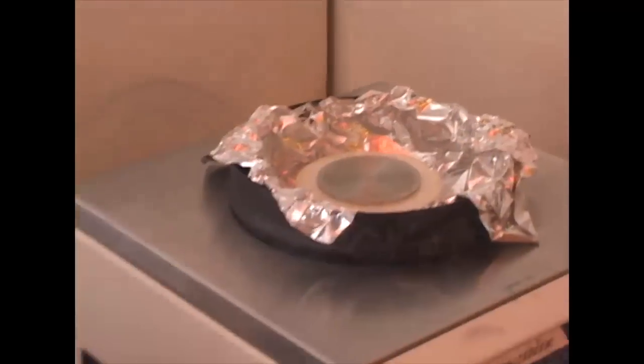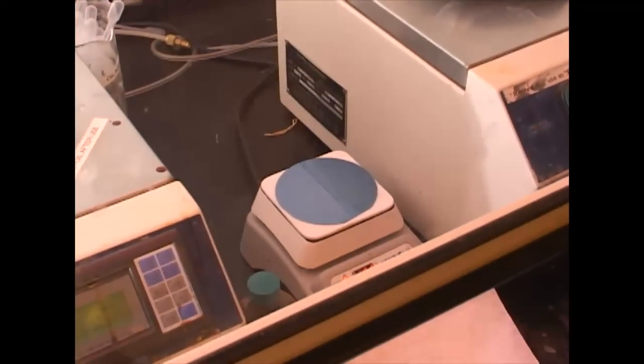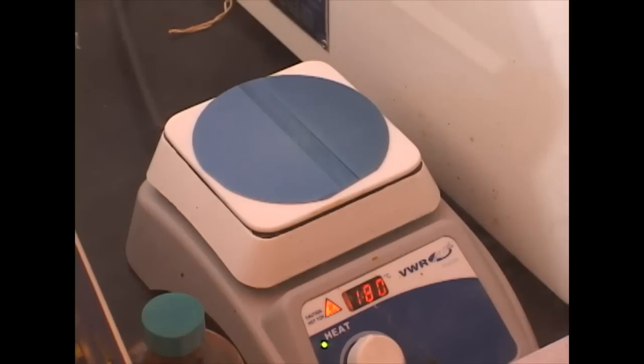Now I'm going to transfer that wafer to a hot plate at 180 degrees for one minute. That'll drive off the excess solvent and solidify the resist.